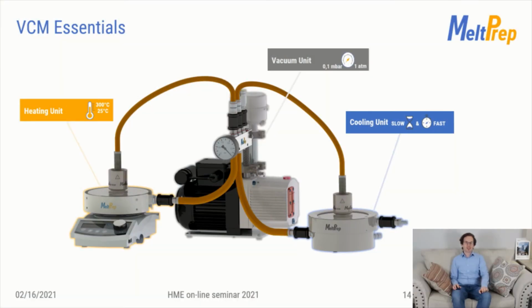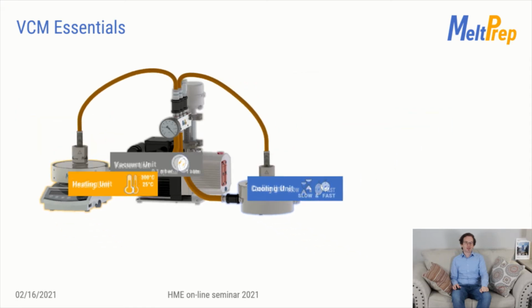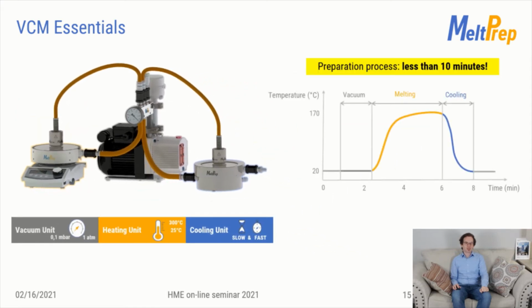Here you can see the entire VCM Essentials again. A typical VCM sample preparation takes less than 10 minutes. Heating is performed in some minutes. It can go up to 300 degrees Celsius, making it suitable for most pharma applications. Cooling generally also only takes some minutes. At the end of the operation, there is no tedious cleaning required, making the process time efficient and lossless.